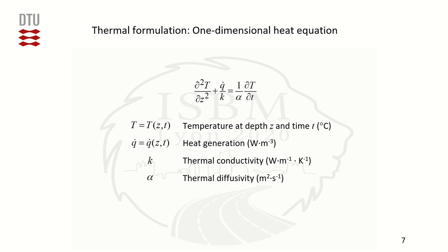A right-handed Cartesian coordinate system is introduced at the surface of the half space, with the z-axis pointing down into the medium. Assuming identical thermal properties and boundary conditions within any plane perpendicular to the z-axis, the one-dimensional heat equation is utilized by considering an internal heat source Q. The solution of the partial differential heat equation is acquired with a forward finite difference scheme, wherein the medium is discretized into thin sublayers of thickness 1 cm. The time is also discretized with time steps of 20 seconds each.